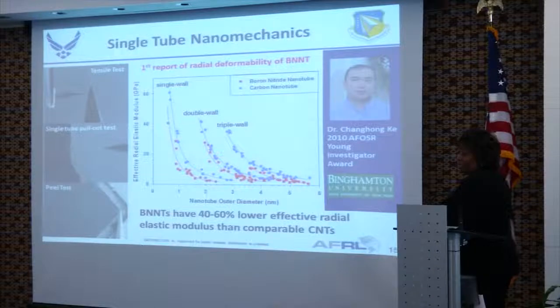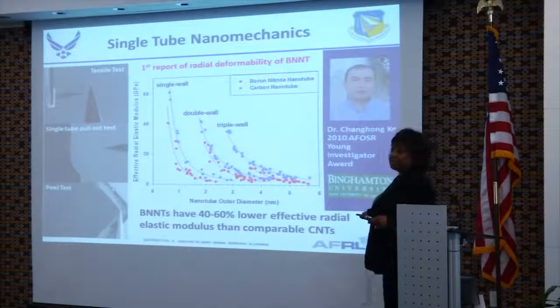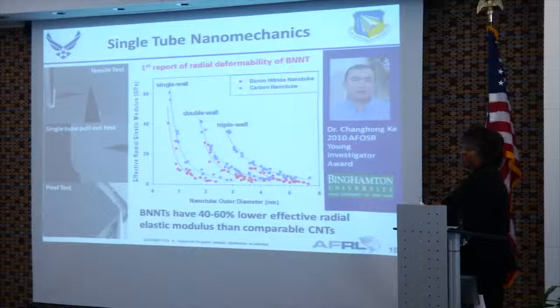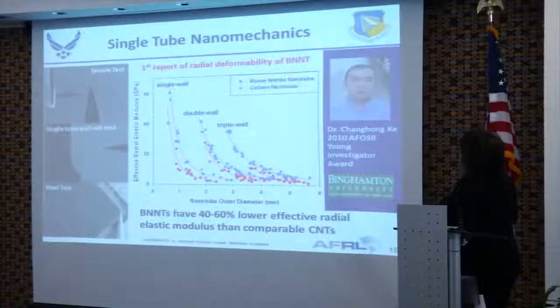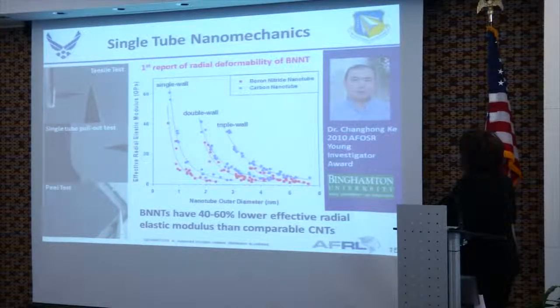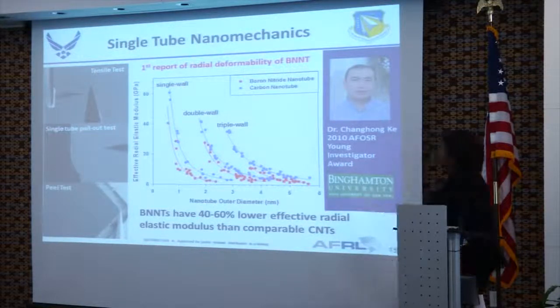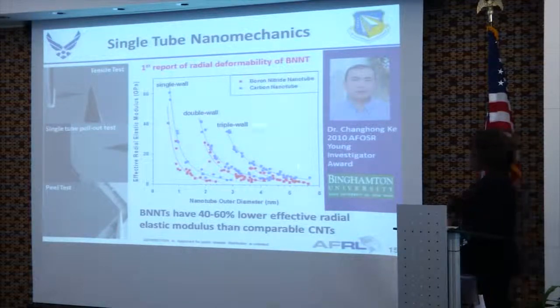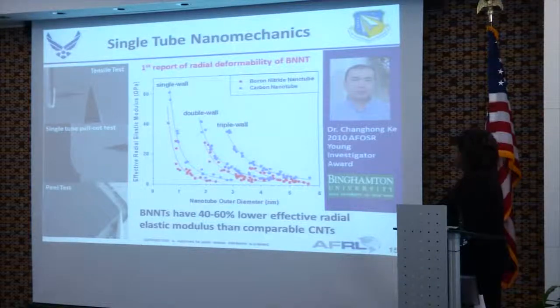I think he and Dr. Cheol Park at the National Institute of Aerospace are about on their 4th or 5th journal publication in this area, because there's just so much exciting discovery going on. But in this case, he's painstakingly separated out single wall, double wall, and triple wall nanotubes, both carbon and boron nitride, and done single tube measurements of the elastic modulus of each of these. The carbon is in blue and the boron nitride is in red. What you see is that the boron nitride nanotubes, for each of these different types of tubes, have on average a 40 to 60% lower effective modulus than carbon nanotubes. This is really the first actual measurement of these types of properties.